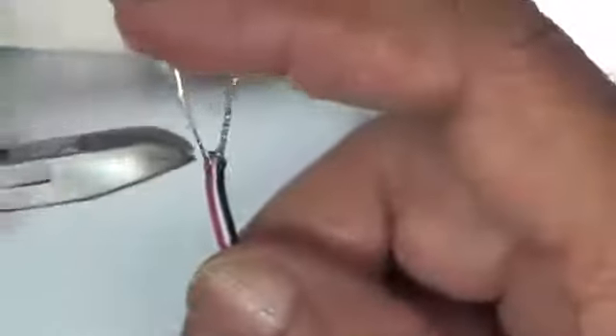Next thing VJ will do is trim the excess length off of the stripped ends of the wire there. And he's going to trim this so it fits within the tinned area of the solder tabs on the strain gauge. Also, before doing the soldering, I'm going to separate the two bundles with a small nick between the red and the rest, so that we have a small amount of flexibility here to be able to align these two on the solder tabs on the strain gauge. Excellent.